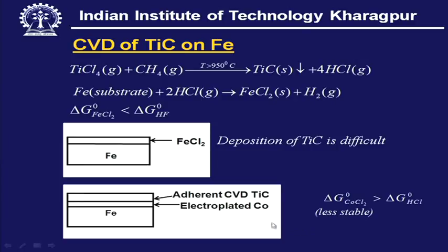So, once this steel is protected, and we get a complete layer of TiC, however small it is in terms of thickness, then this HCl cannot attack the substrate surface, which is already covered with TiC. That means, in all CVD reactions, the process parameters at the beginning have to be chosen in such a manner that this